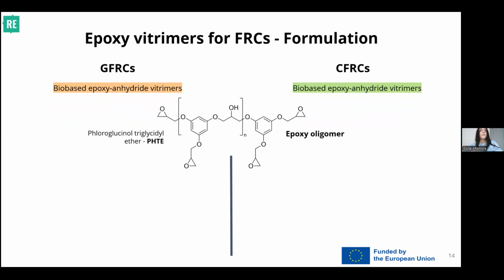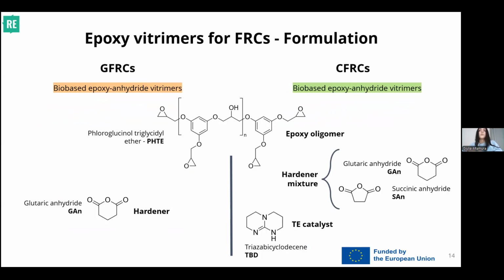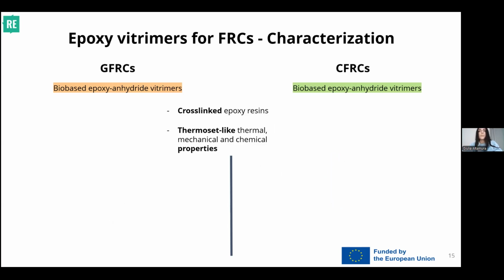As for the first formulation, this is pretty simple. It's a two-component formulation that also employs glutaric anhydride as hardener. In the second case, we have used a mixture of anhydrides and a transesterification catalyst to help the exchanges between hydroxyl and esters. This catalyst is called TBD.